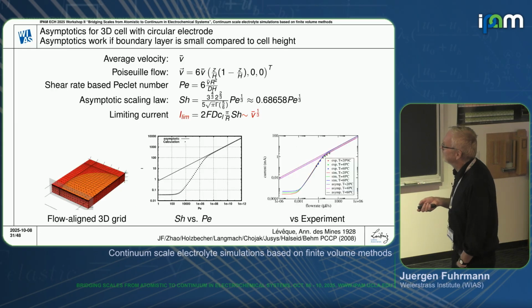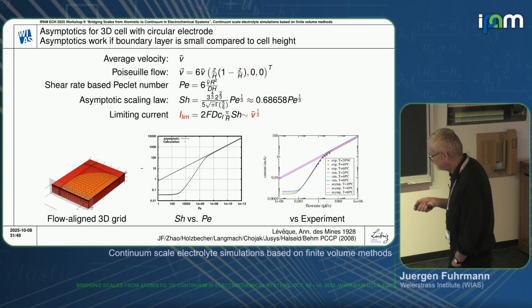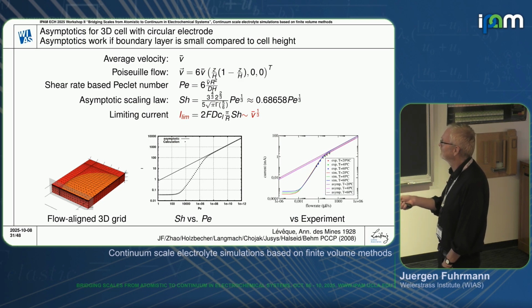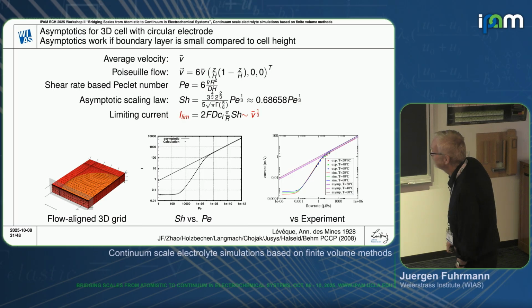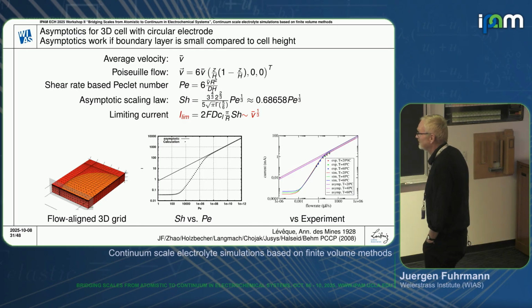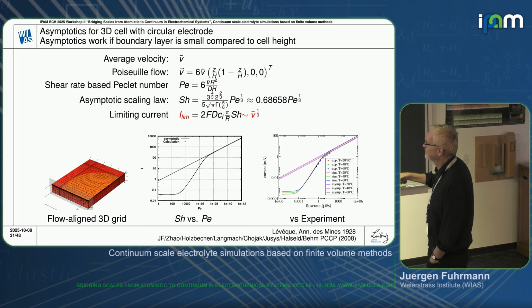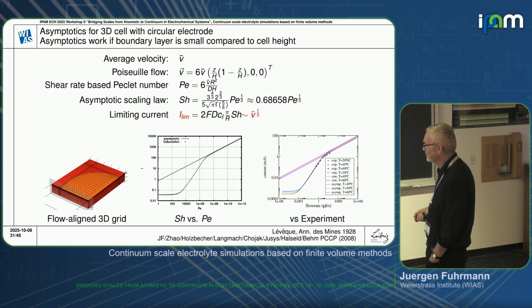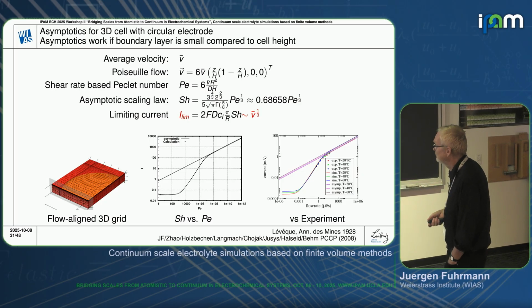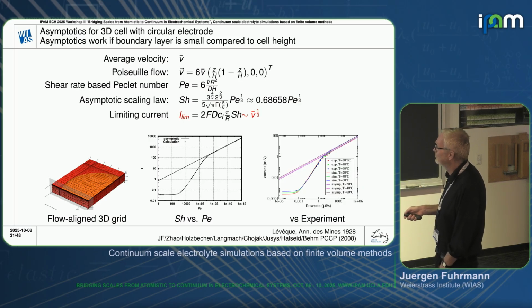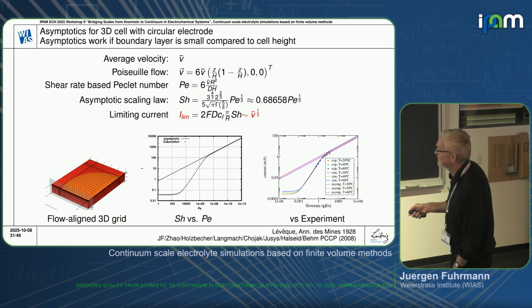And we did this experimentation and compared this with experiments in the Behm group. And there's the theory by Levesque in 1928, that the limiting current is proportional to the third root of the velocity. So this can be derived by asymptotic theory. But the tricky thing is that this is only true for large velocity. This is a large velocity asymptotic.